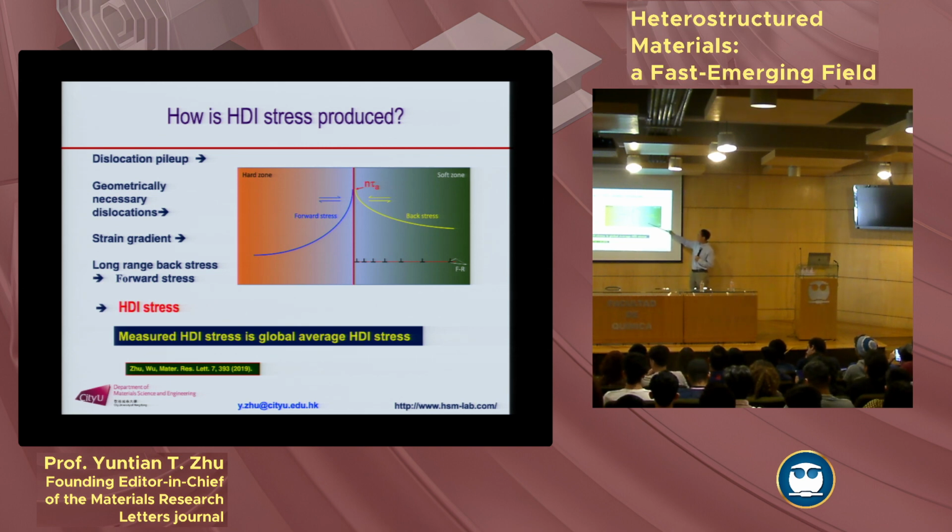all these dislocations have a repulsive force to prevent further dislocation emission or slip, which means it makes this soft zone appear stronger. The strength might be 300 megapascal, but at 500, it will stop. If you want to emit more dislocations, you have to increase the load further.